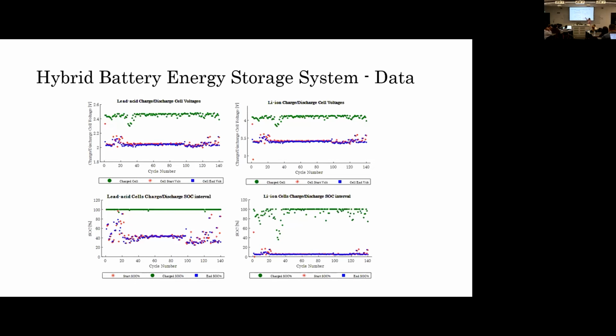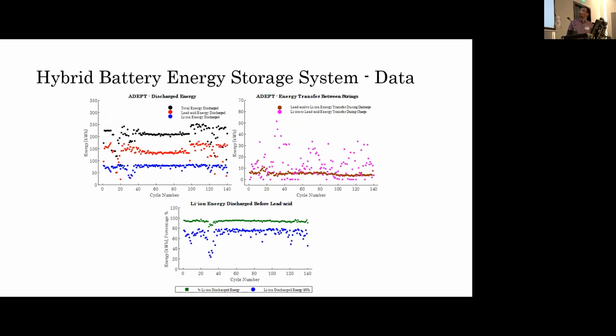Oh, by the way, each one of these dots represents a cycle. So I've taken around 140 cycles on that, right? Okay, so that's the lithium ion, from around 3.4 to 4 point something volts. You can see the system was charged up and down from around 40%, charged to 100 and back to 40. It was not taken from 0 to 100 and back to 0. We don't want the battery, especially lead acid, to be at 0%. Lead acid, on the contrary, was cycled differently, from around 5, 10, 7% to around 100 and back. Hopefully that gives you an indication of how the system was run.